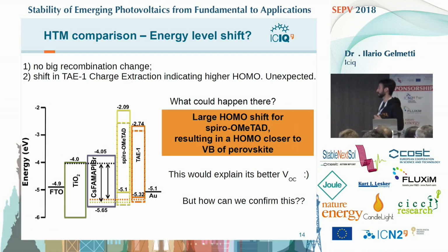So what we thought is maybe the HOMO level calculated by cyclic voltammetry is really wrong when the layers are deposited on top of perovskite. As you can see, we are using a cesium, formamidinium, methylammonium, so this triple cation perovskite. So we thought maybe there is a shift, and this shift is much bigger for the spiro-OMeTAD than for the new molecule. So the resulting HOMO level is closer to the valence band maximum of the perovskite for spiro-OMeTAD rather than for the new hole transporting material. This could explain why we have this unexpected VOC change.